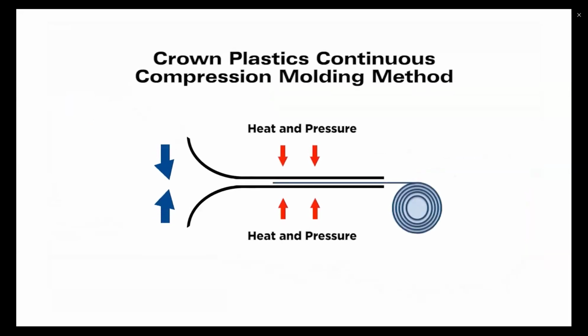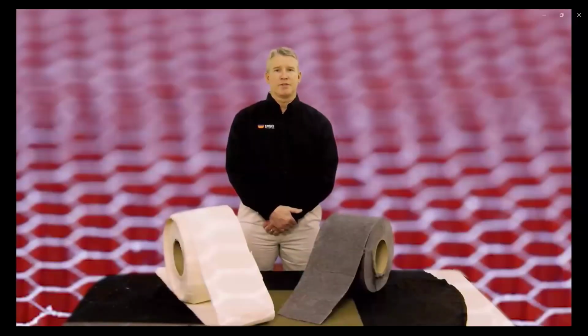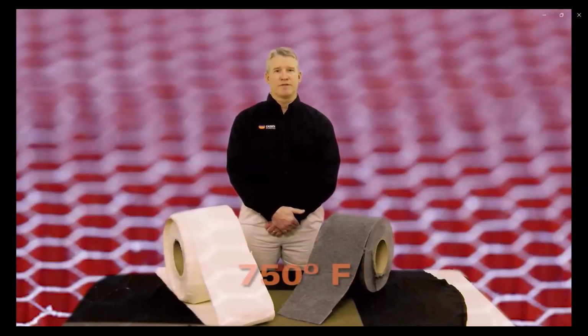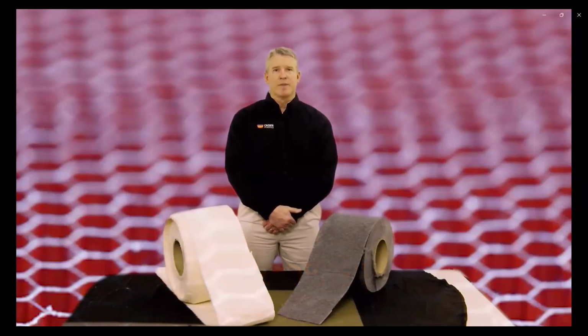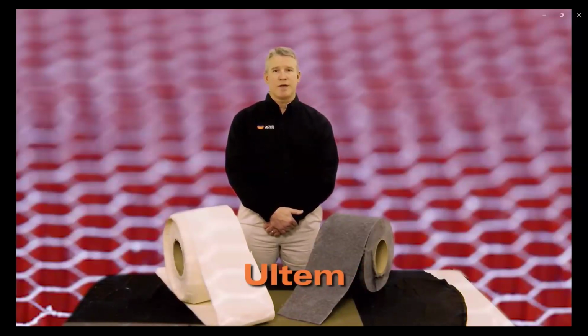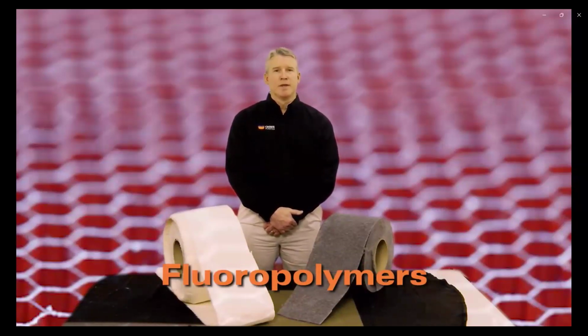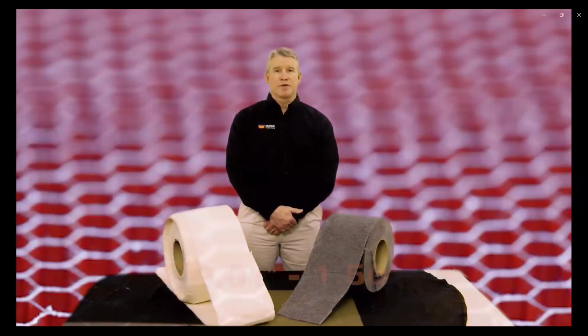The unique process is basically two endless stainless alloy belts that heat, compress, and cool in a continuous fashion. This process has the ability to achieve up to 1,500 psi of isochoric molding pressure with a maximum temperature of 750 degrees Fahrenheit. This high pressure, high temperature capability allows for the processing of high temperature engineering polymers like PEEK, PPS, Ultem, nylon, and fluoropolymers. Thickness possibilities range from 0.010 of an inch thick for thin film composites up to over 1.5 inches for surface lamination of honeycomb and other core materials.